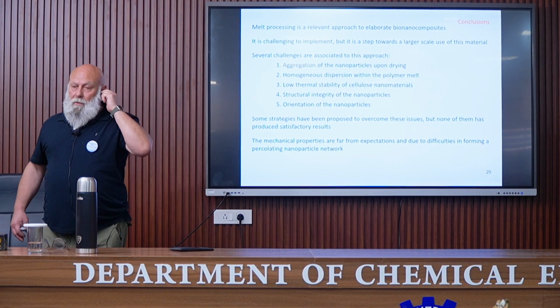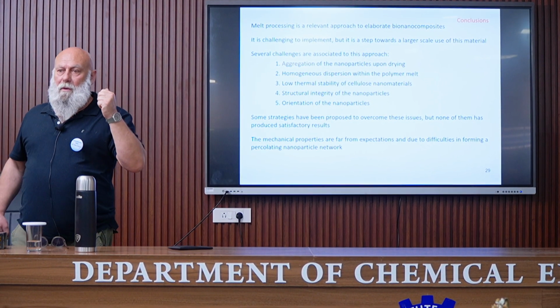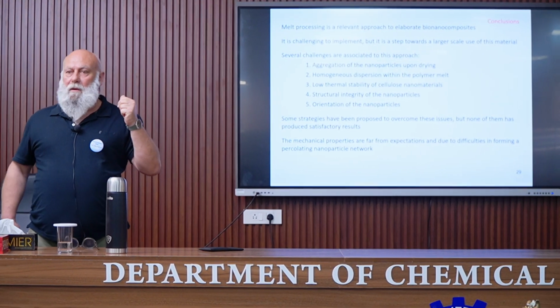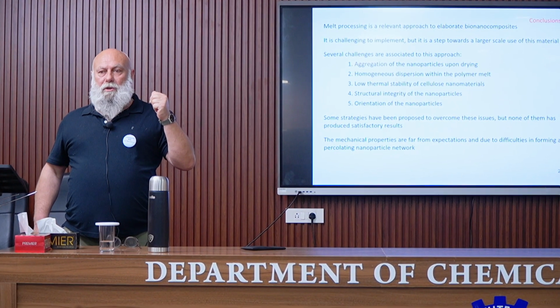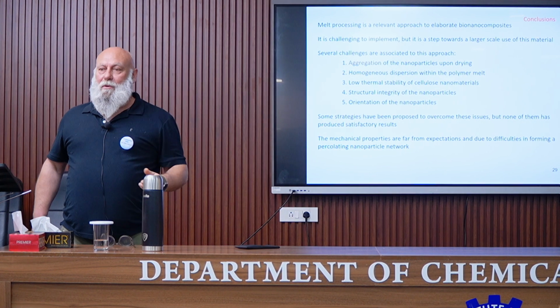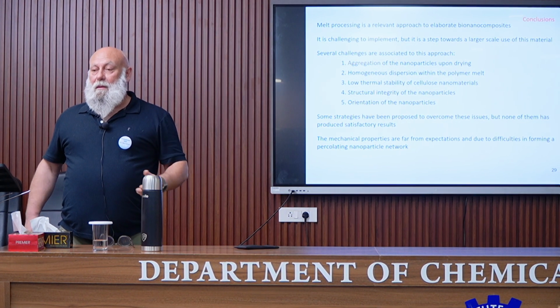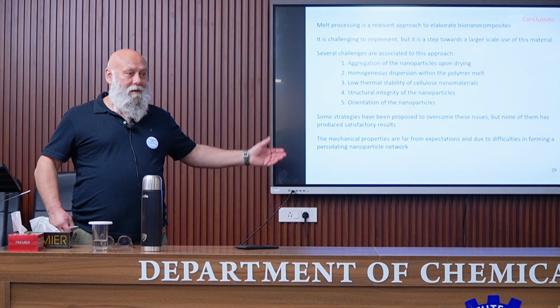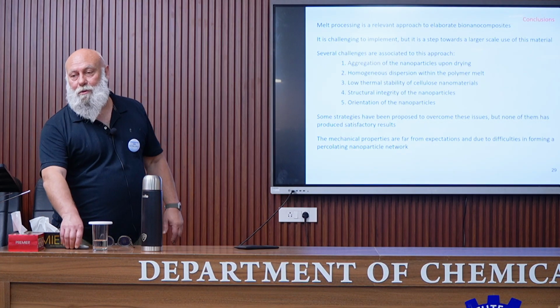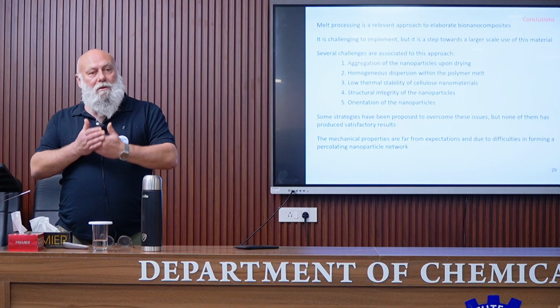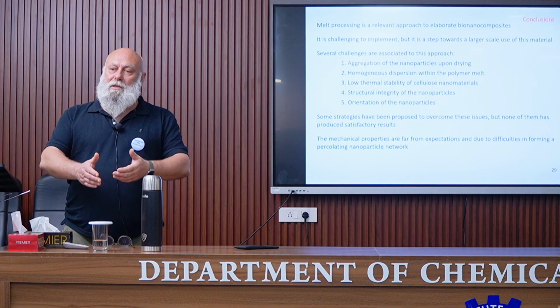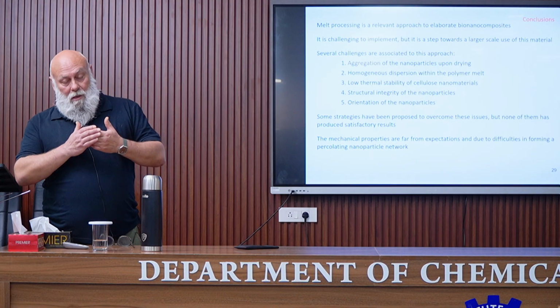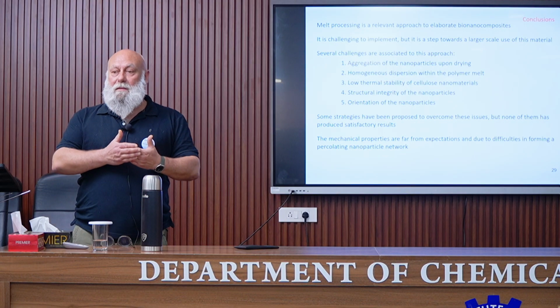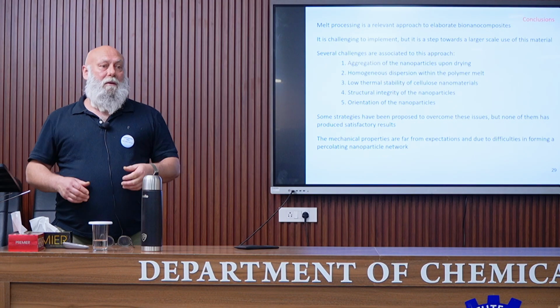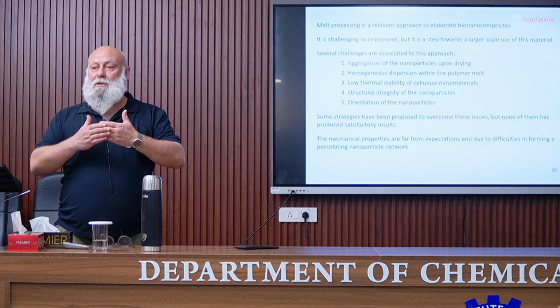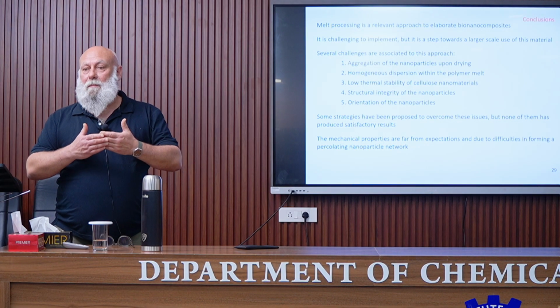Compared to the first study that I showed you, which was published in 1995, nobody reached the same reinforcement effect. So, this extrusion can be good, but you see the problem. You have to avoid the aggregation, you have to promote the dispersion, so it means that for this you need to block the OH groups from the surface, but for this, of course, you limit the interaction between the nanoparticles.